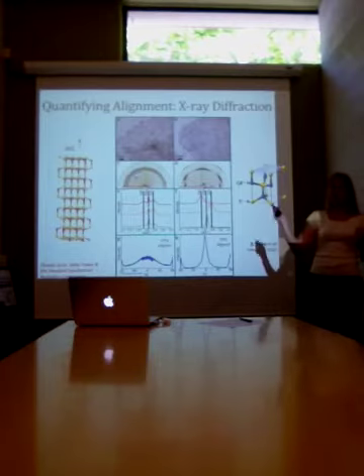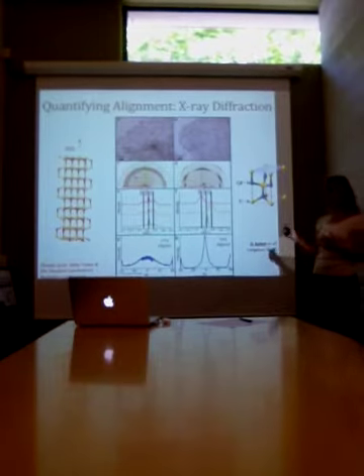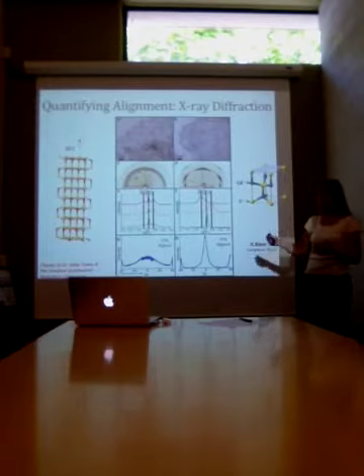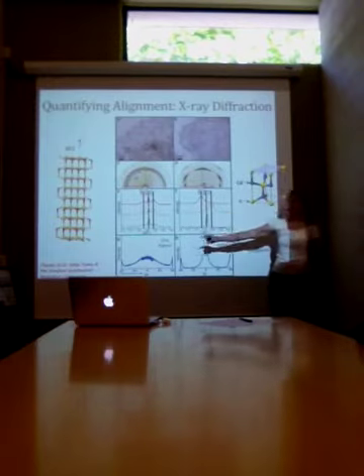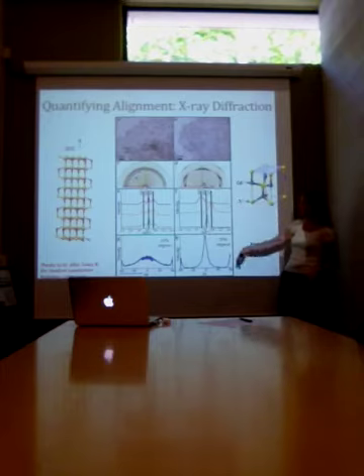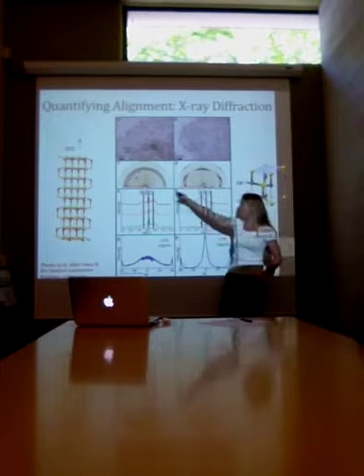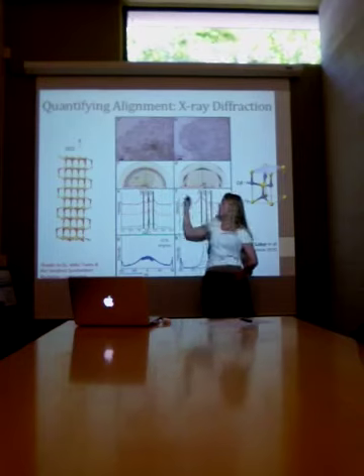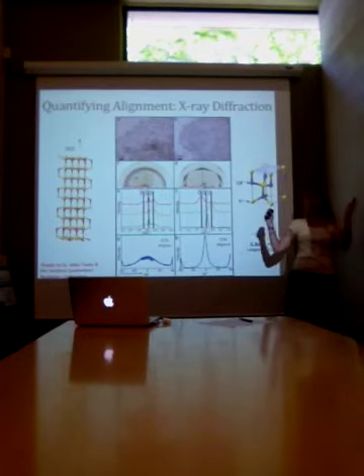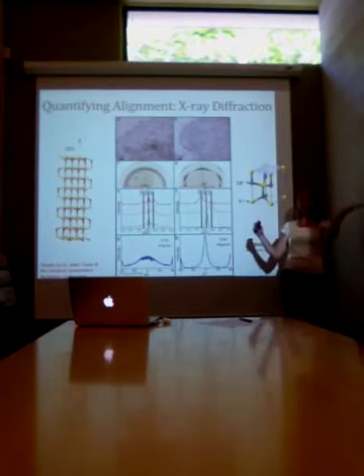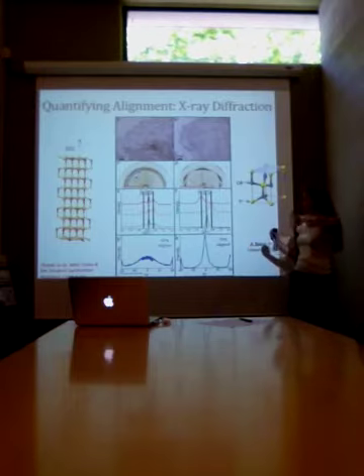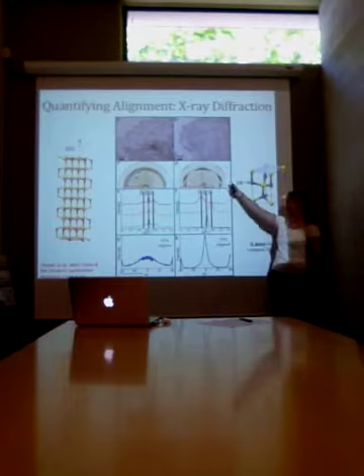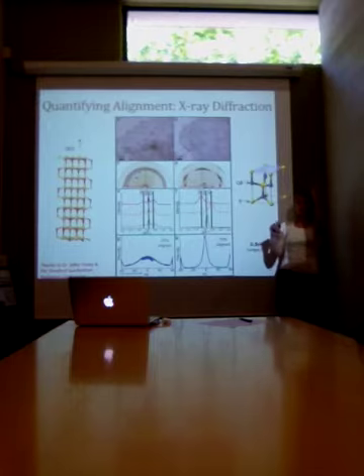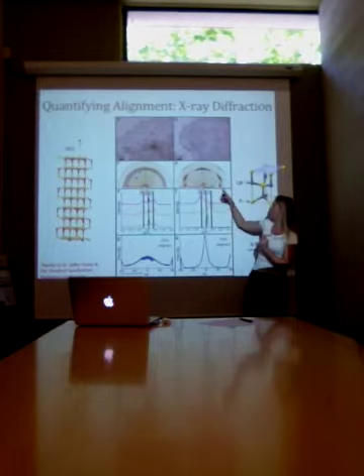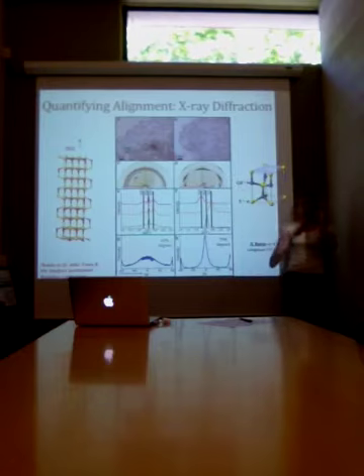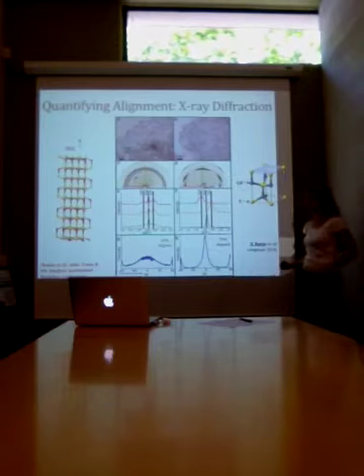Our cadmium sulfide nanorods have an anisotropic Wurtzite lattice that allows us to do very much the same thing. So you can see on the left-hand column data for unaligned rods, and on the right hand data for aligned rods. The left, this dark circle, is where we're seeing diffraction events. And you can see they happen at all angles, meaning that rods are standing at all different angles. Whereas in the case of aligned nanorods, they're occurring up here and down here. And this is from a different diffraction event in the crystal, a different crystallographic direction.